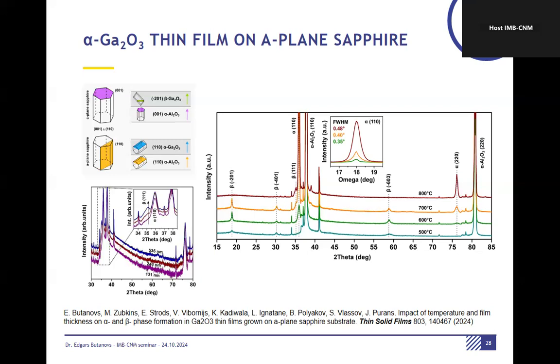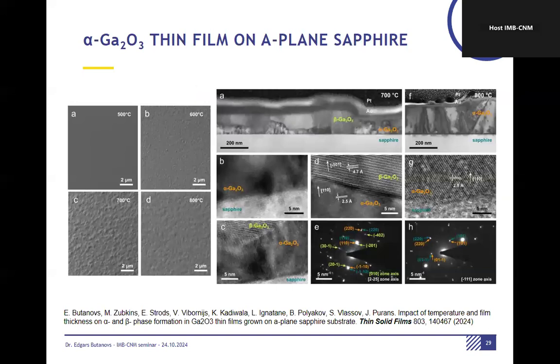This is mainly probably related to, first of all, diffusion. So the deposition rate is slower, so there's more time for this epitaxial stabilization, to let the atoms find the correct positions on this substrate. That's one thing. I think that's one of the main reasons. We also studied the thickness dependence. What we noticed is that if you have thicker films, there's a mixture of both alpha and beta phase. And typically when you have thinner films, it's easier to stabilize this alpha phase. And then we did a TEM study to see how it looks.